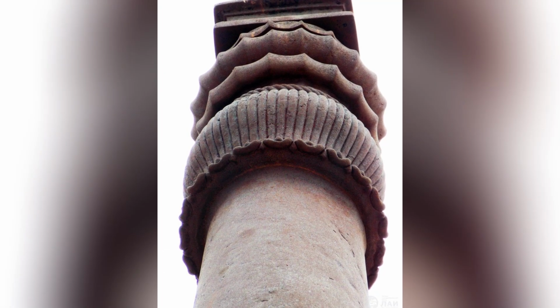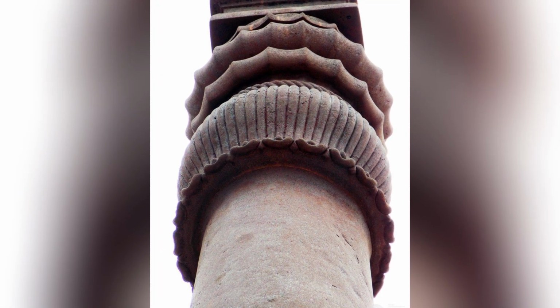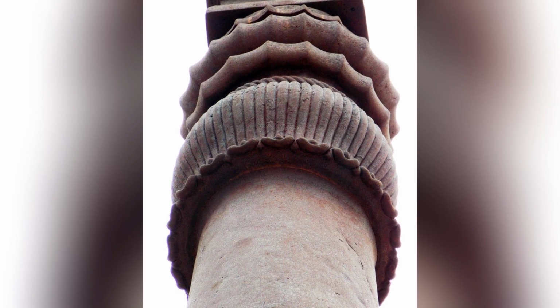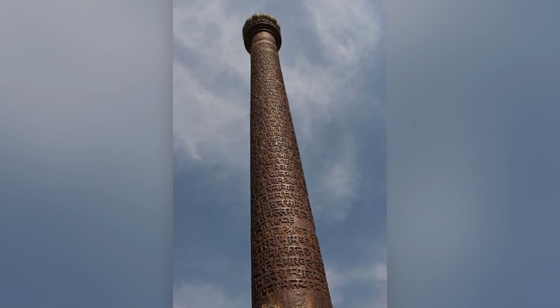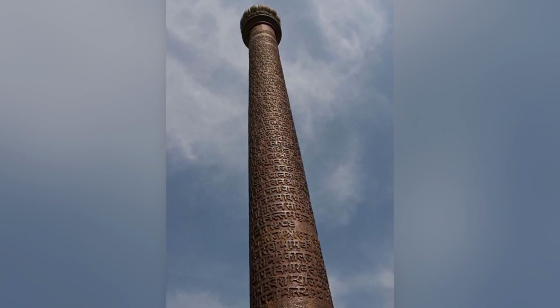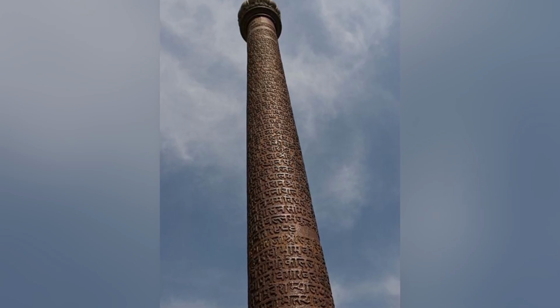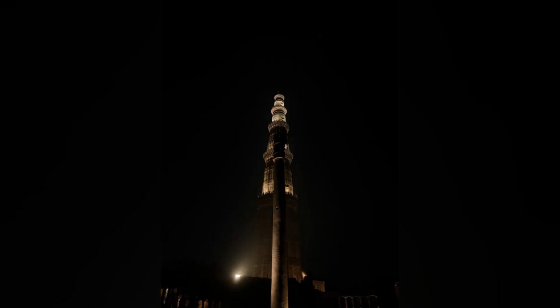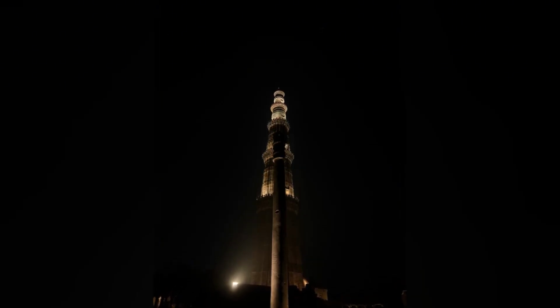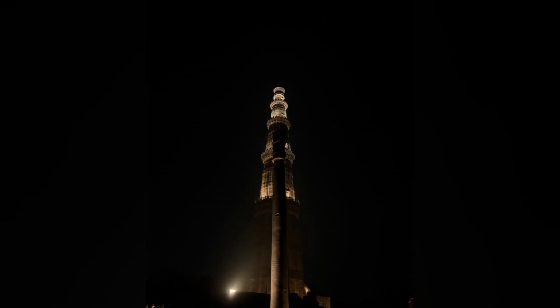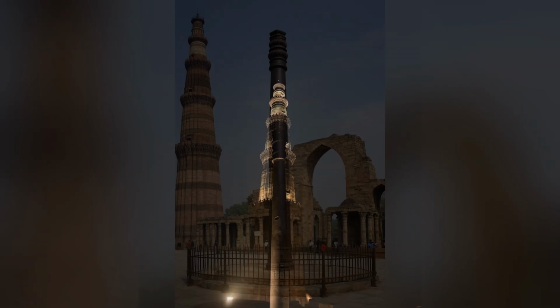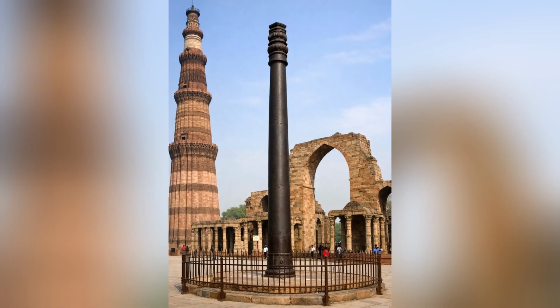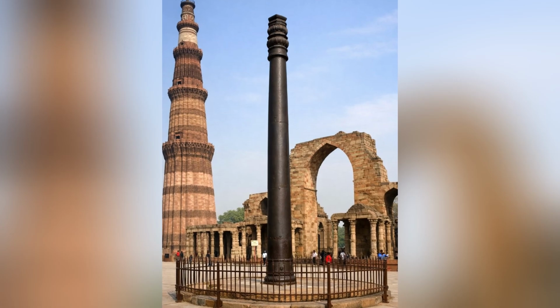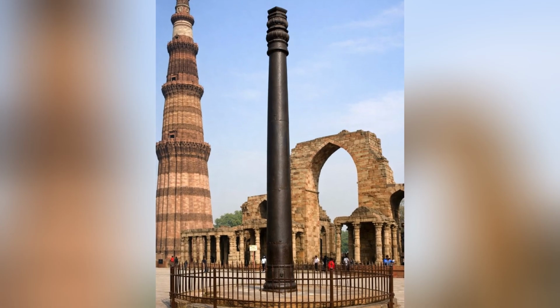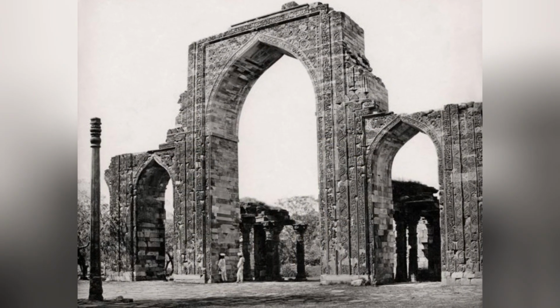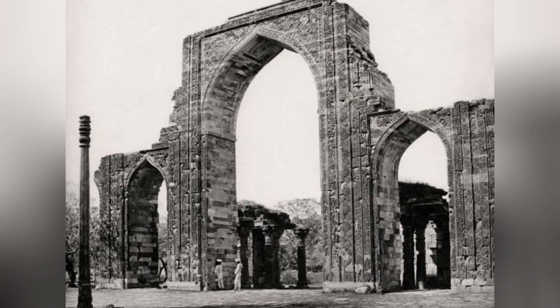has been investigated by researchers who have analysed the outermost layers of the film for the presence of pollutant species, such as sulfate and nitrate ions, that are characteristic of the industrial and vehicular pollution in modern urban environments. The analysis has revealed that the outermost layers of the film do contain traces of pollutant species, but that these species have not penetrated into the deeper layers of the film and have not compromised the film's protective capability. The film appears to be resistant to the corrosive effects of modern atmospheric pollution, a finding that is consistent with the continued preservation of the pillar despite the increasing pollution of the Delhi atmosphere over the past century.